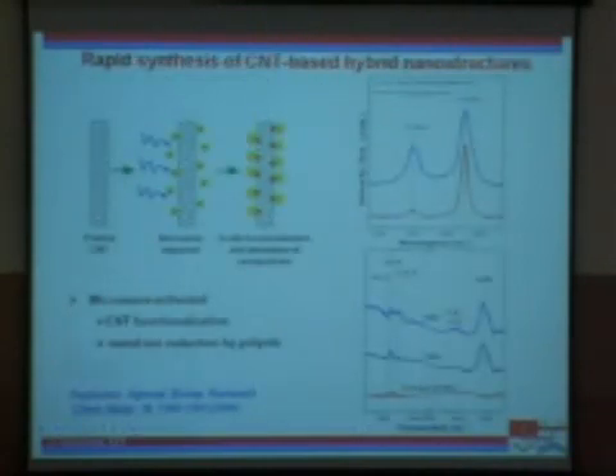Okay, let me show you a different strategy of derivatizing nanotubes with other kinds of quantum structures. I'll show you 2 examples. And here the emphasis is on creating large quantities of these hybrid structures as opposed to organizing them. The approach that we took was to use microwaves. We take nanotubes, and we also take metal ions and just microwave it. By reducing the metal ions, we get either metallic nanoparticles or semiconducting nanoparticles, depending on what chemistry you use. And you also functionalize the tubes because of interaction with the microwave and the water and the carbon nanotubes.